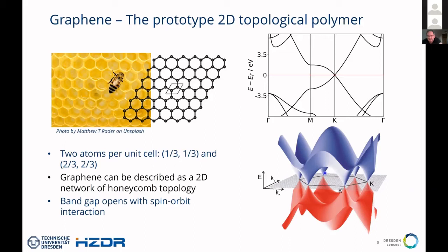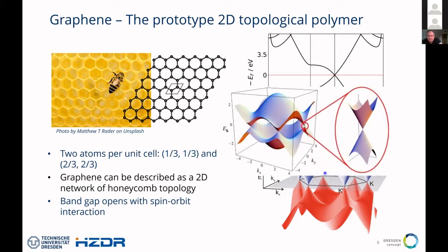And if we draw that for graphene, people have observed a very special feature, and physicists got all excited about it, and that is a so-called Dirac point. So if we zoom in here, we can see this cone, okay? And at the center of this cone, you have just a point. The particular part about this is if you calculate the effective mass of the electrons, that is given by the curvature of the band structure, we would have a kink here.